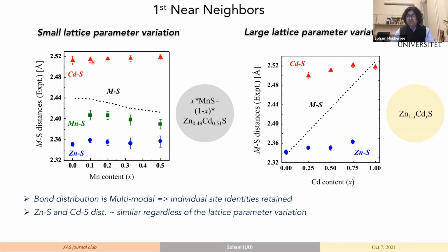So the lattice parameter change between the two end members hardly has any effect on the local metal to sulfur bond distances. So in either case, the metal-ligand distance is extremely well reproduced.